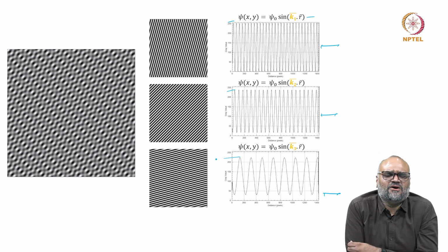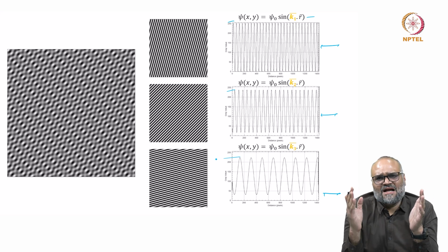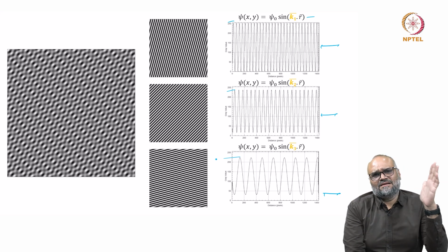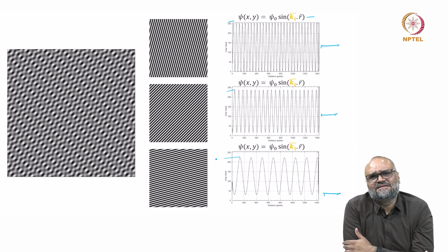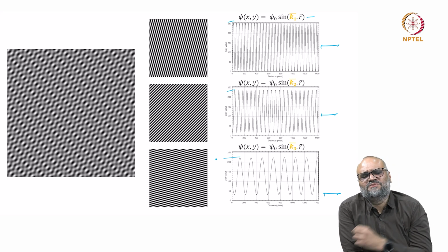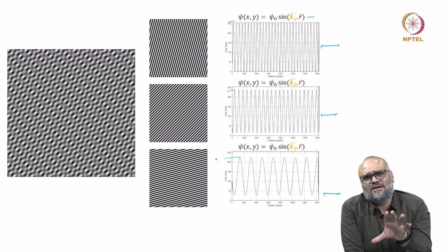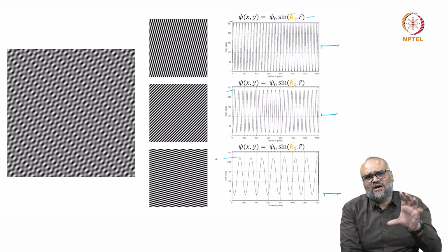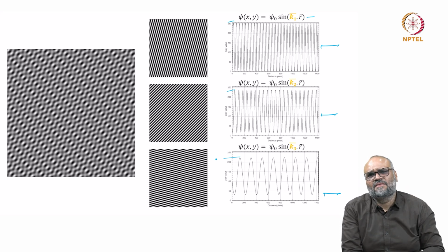I've tried to impress upon you that there is the image plane, there's the back focal plane, there's the object plane, and when an electron wave or light propagates through these lenses, you simply have a mathematical modulation which can be represented by a Fourier transform. We'll look at more effects of this, and what I've also not discussed explicitly here is that when these modulations are happening, I'm also causing a phase shift and an amplitude change.